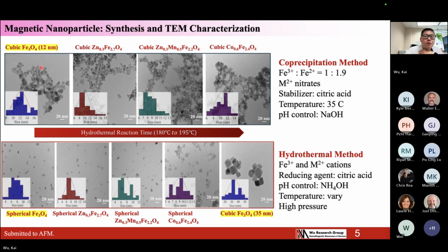So overall, in this topic, I'm going to present the characterization of these lab-produced particles. We have 5 cubic particles with different doping, zinc, manganese, and cobalt doping, around 10 nanometers in size. We also have 4 spherical particles produced by the hydrothermal method, with 10 to 12 nanometer size, and also with zinc, manganese, and cobalt doping. One exception is the cubic nanoparticle with 35 nanometers for comparison. So today's talk, I will cover the characterization of these 9 particles in their physical properties and biomedical properties as well.